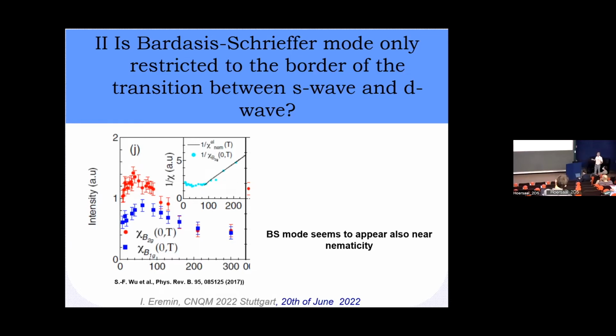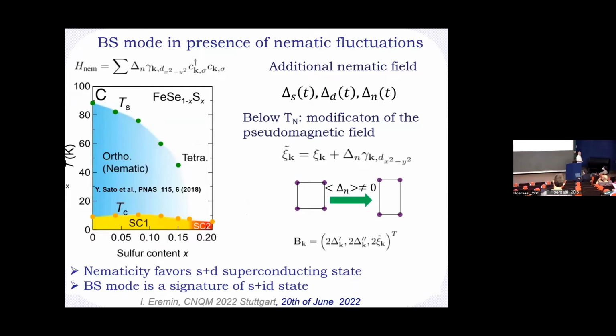already starts to increase well above the superconducting transition temperature, and is actually attributed as a signature of the nematic fluctuation, which orders around 90 K, and this is also the reason why you have a drop of this intensity below the nematic transition. So the question is, you cannot consider in this system the Bardasis-Schrieffer mode alone. You have to take into account that there is also nematic fluctuation. Which basically means that you have to come back and reconsider your problem. And in this case, this is a phase diagram of one of these nematic superconductors, where you see that you can continuously tune the structure of the nematic transition from being much higher than the superconducting state, but also towards temperatures where they become closer and closer together.